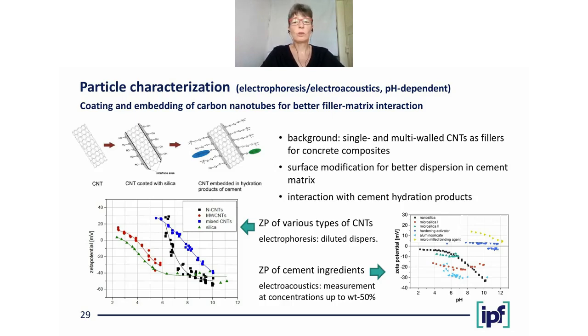And yes, what we did at the left hand, you see the zeta potential of different carbon nanotubes prepared in different ways, and you can see due to the different surface functionalities, they have very different behavior, from rather acidic, the red curve, or amphoteric more, to rather alkaline, the black and blue curve. This was done by electrophoresis, and for comparison, we also measured the zeta potential of different ingredients of the cement in the original concentrations, and for this we use the electroacoustics measurement.